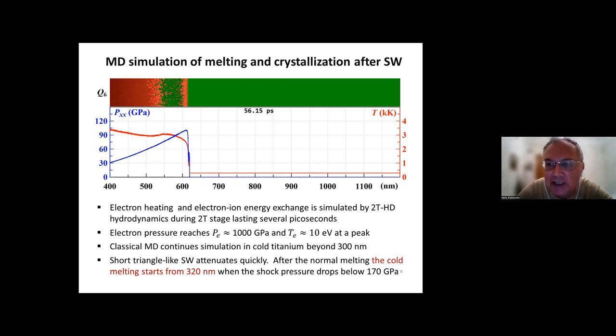Oh, a lot of additional difficulties appear. Of course, cold melting depends, first of all, on the orientation of the single crystal. So we performed simulations of 3 main different orientations of our titanium sample. In all 3 cases, we found 3 different depths where the melting ceases. It depends on shear stress, because the shear stress depends on orientation in uniaxial compression. The thickness of the melting zone is sensitive to orientation, though not significantly, about plus or minus 100 nanometers. Here we have about 800 nanometers of melting depth, but with a different direction, plus or minus 50 to 100 nanometers can be obtained. It is discussed in the paper.